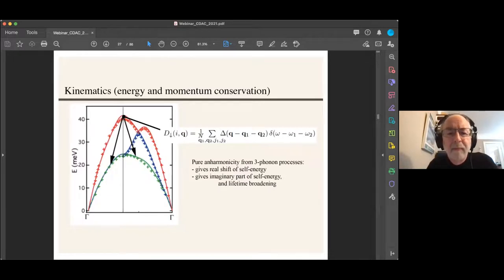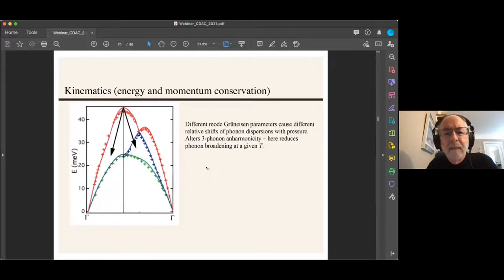For one of them, and we'd have to have many of them, of course, but what might happen is that under pressure, the different Grüneisen parameters for these different modes could change so that, for example, this mode might move up faster than these do, and then we lose these three phonon processes. So this is the sort of thing that I think we can find in the pressure dependence of the anharmonicity, and we'll be seeing some combination effects as we increase the temperature and the pressure in these contributions to the free energy and in the phonon frequencies.